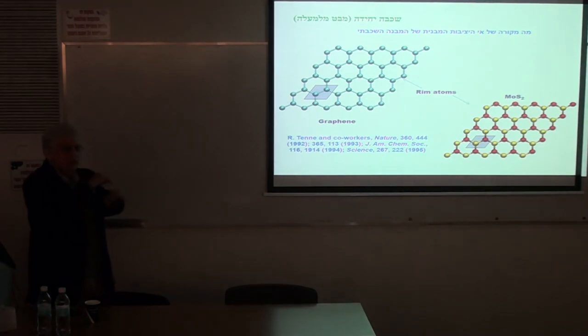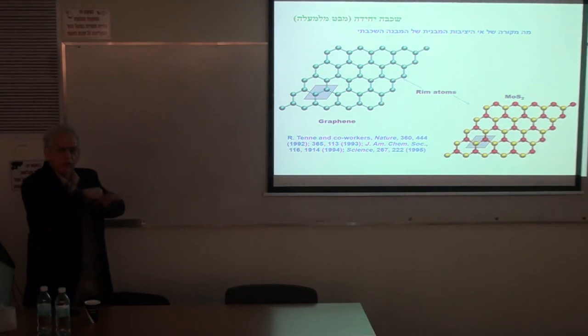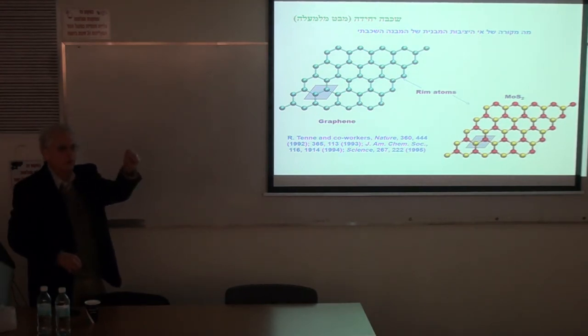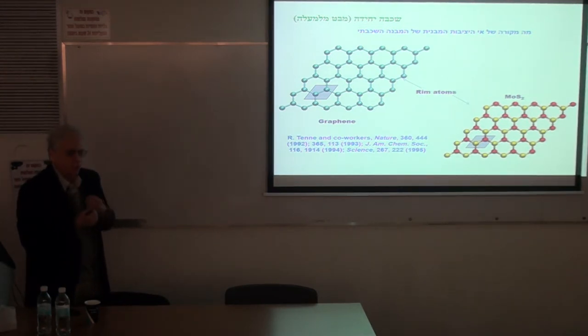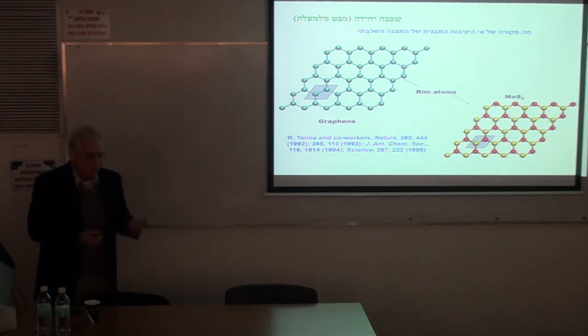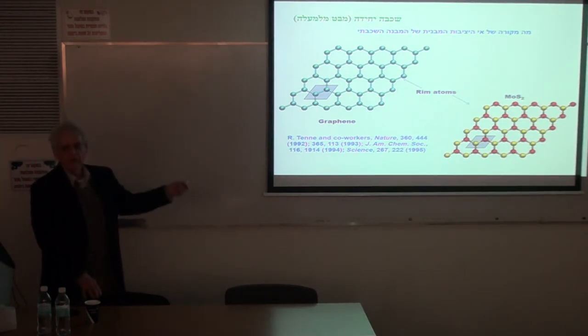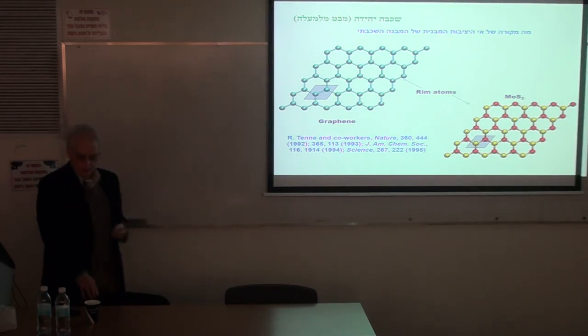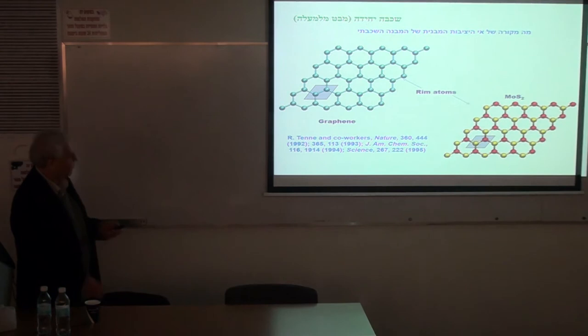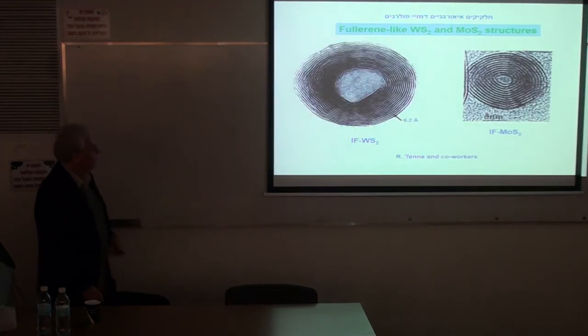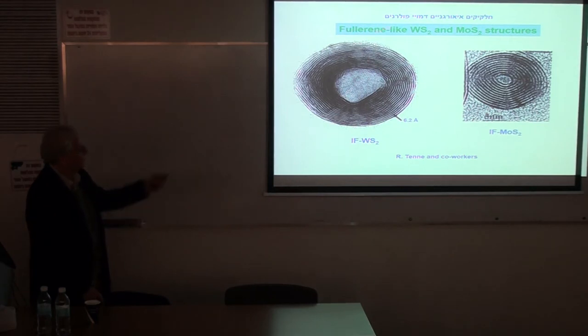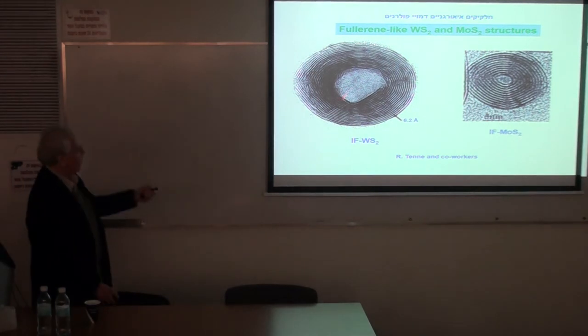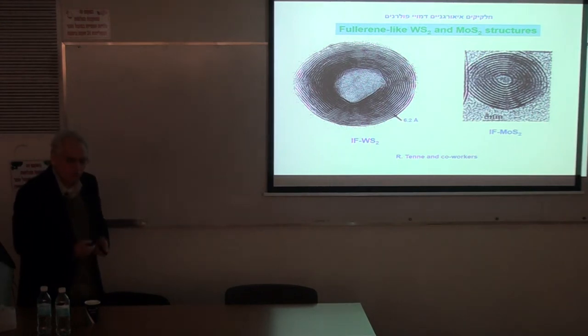And then when you go to the nano realm of nanoparticles, they spontaneously fold and close into closed structures. And if you learn how to cook them properly, you can get pure phases of these nanotubes and fullerenes from a variety of inorganic compounds. I won't go into the details, but I'll show you just a few examples to that effect. These are the first fullerenes from tungsten disulfide and molybdenum disulfide. You see that, unlike C60, they are multi-wall and have many defects, but they are all hollow closed structures.